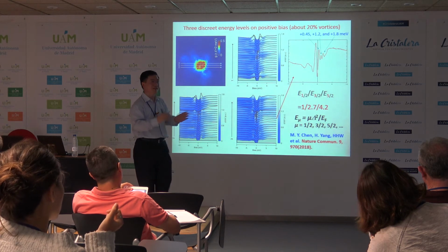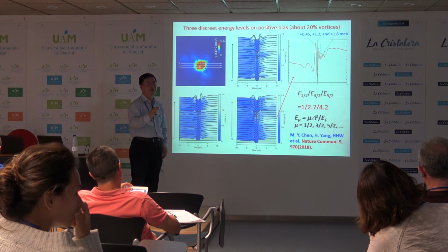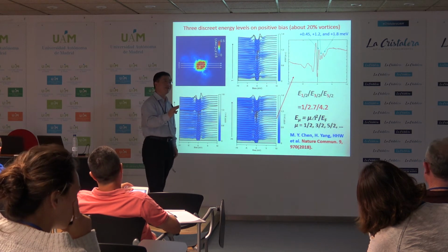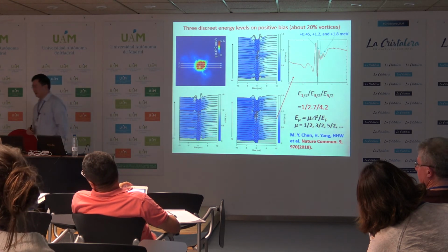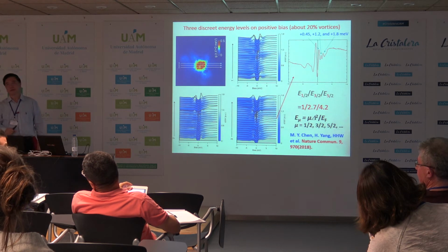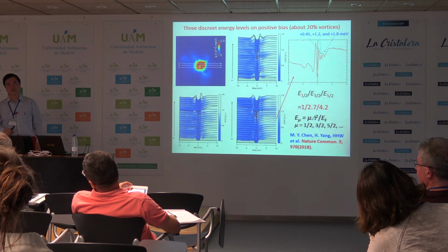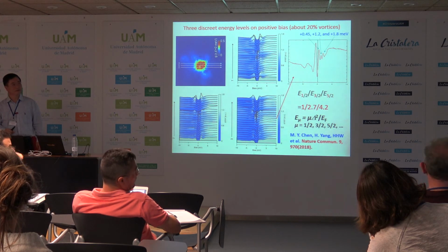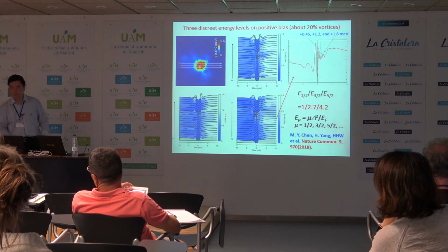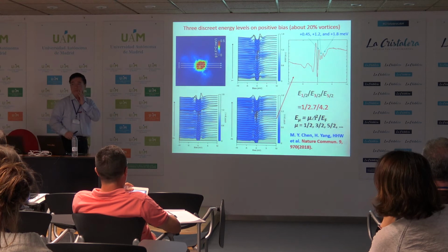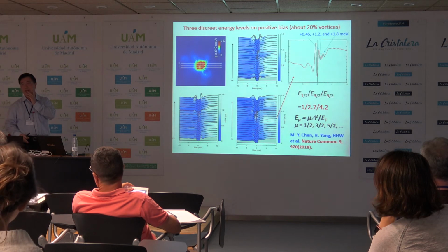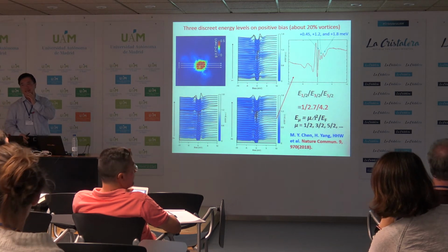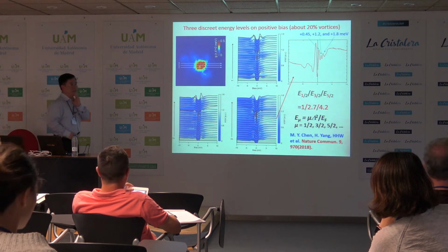Okay, that's something I don't understand. If we have nothing topological here, then it should be like that. Would it? All particle-hole asymmetry effects depend on delta over epsilon F. Suppose you have a quadratic band. If delta is very tiny, you don't see it, it's just like a flat approximation. But if delta becomes large, you begin to see it. But I think in the calculations of Machida, they show some particle-hole asymmetry. And I guess this asymmetry does not depend on the field direction. Yeah, it does not depend on the field direction, it's from the band structure. I see.